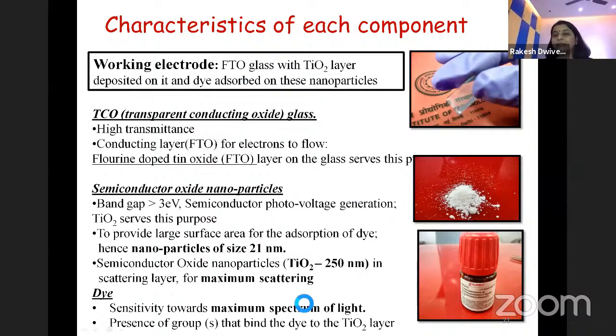And the dye. Students from a chemistry background can really work on the dye part. The dye should cover the maximum spectrum. People are working on blending 2-3 dyes for DSSC application, or on different dye structures, but there is a requirement that the dye should get attached to the TiO2 nanoparticle. Some bonding should be there. Students from a chemistry background can work on getting a dye of maximum absorption spectrum.